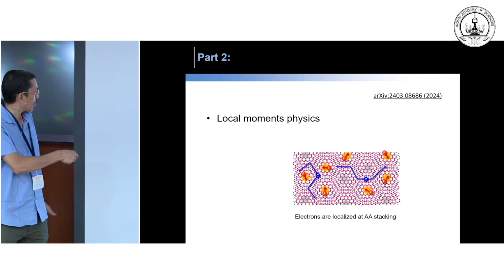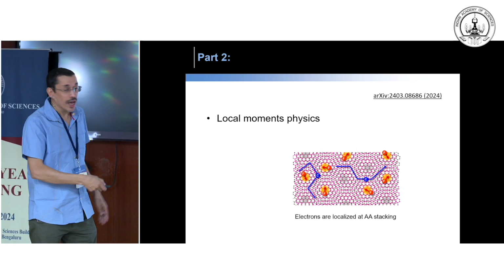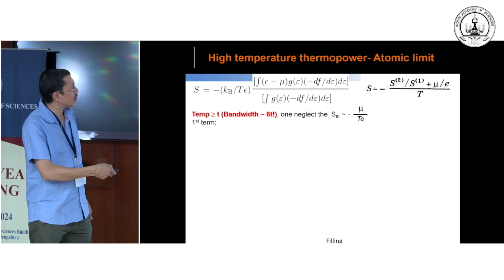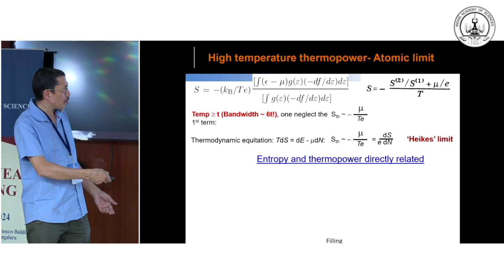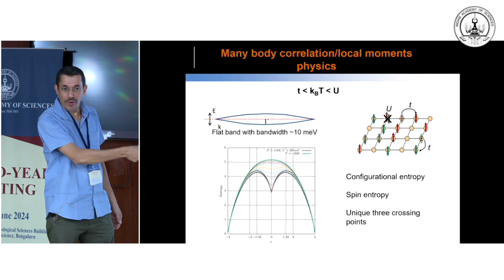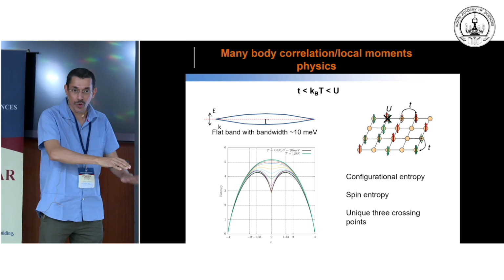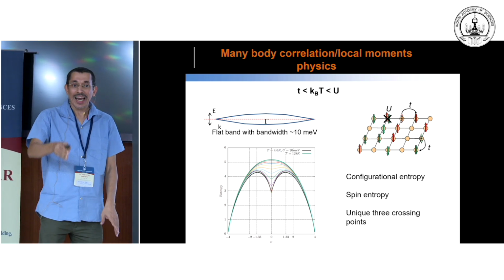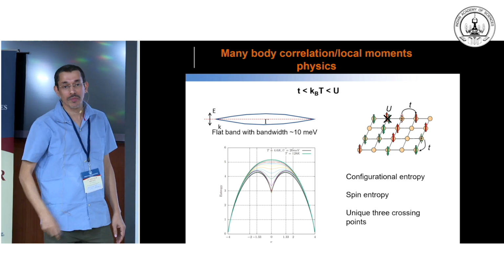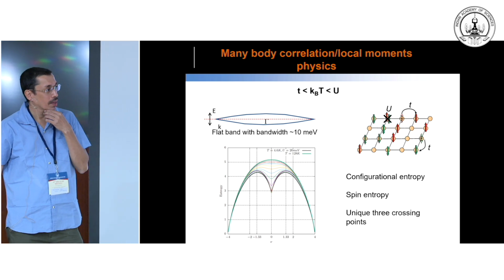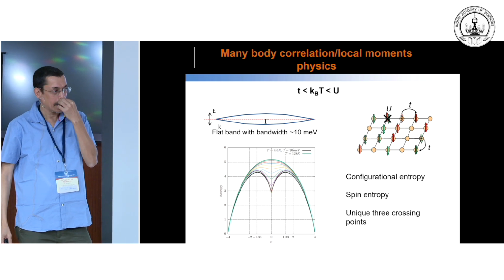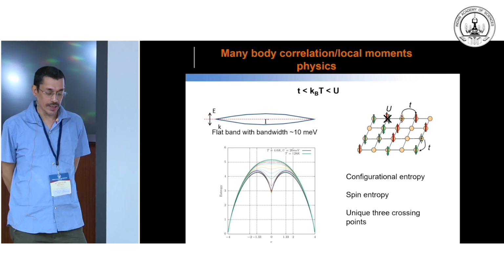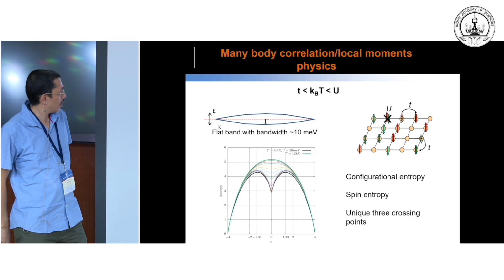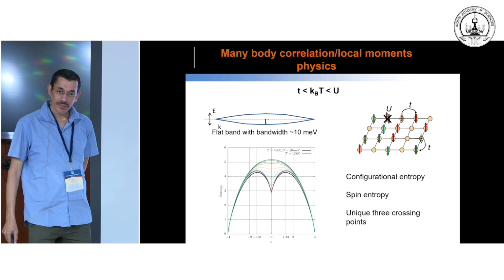Yeah. So people are talking about now heavy fermion, this kind of physics. This was my second part where I was talking about these local moments, and you are indeed right that for that kind of local moment, there is a toy model you can use, and this kind of atomic limit calculations. You can do an atomic limit toy model, and indeed you are right that you can show very large thermopower for this system. Think of these AA regions as a larger network of wires. Right. They're connected, but I think it's mostly that these are localized. The electrons are localized at these points, and they weakly hop.